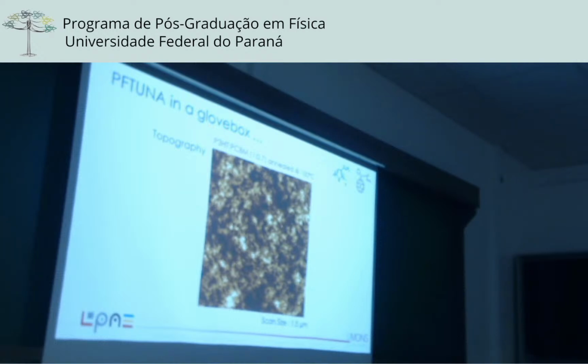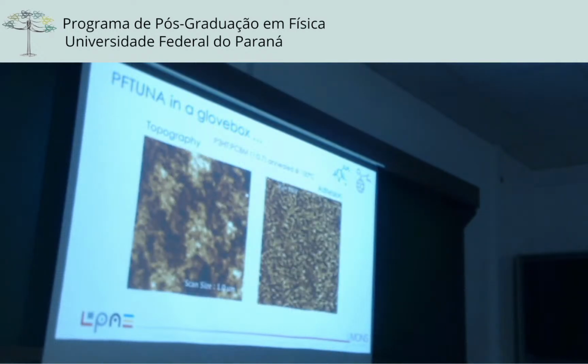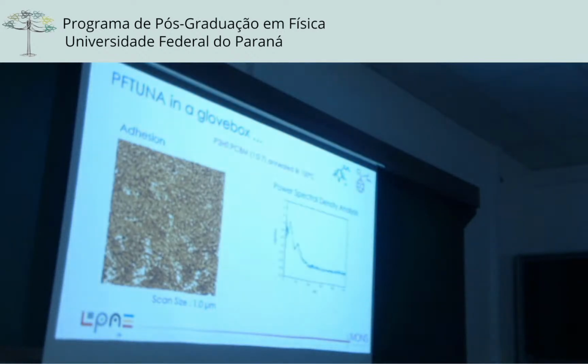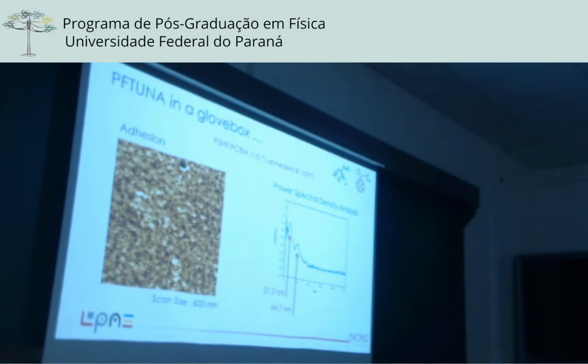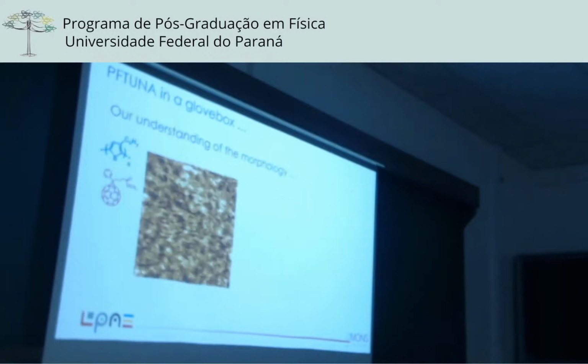But since we are measuring the mechanical properties with that, if you have a look at the adhesion, you start to see something. You start to see some fibers. You can see some domains. And you make a power spectral density analysis. You have two peaks. One at 20 nanometer, which corresponds to the width of the P3HT fibers, and another one at about 65 nanometer, which corresponds to the average size of the PCBM domain.